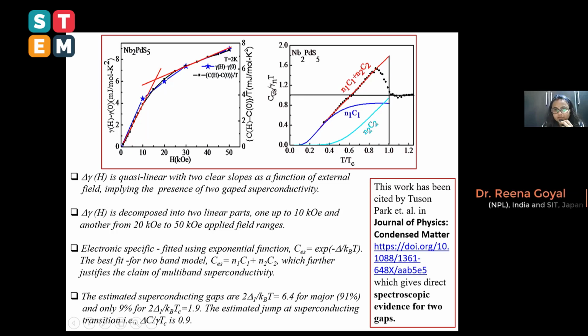And this is the electronic specific heat versus T plot at reduced temperature, and it has been fitted using the exponential function, minus delta by kBT. This curve has been fitted using a two-band model, N1C1 plus N2C2, which further claims multiband superconductivity. The superconducting gaps in this case were found to be 6.4 and 1.9 respectively.